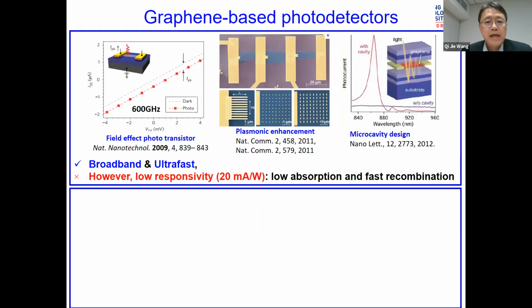So for graphene photodetectors, a number of devices have been developed over the years. The intriguing property of graphene is that it has a high mobility, and the theoretical prediction of the response speed of such a detector can reach 600 gigahertz or more. However, because graphene is only one monolayer, the absorption is quite low, and therefore it has low responsivity, only tens of milliamperes per watt.